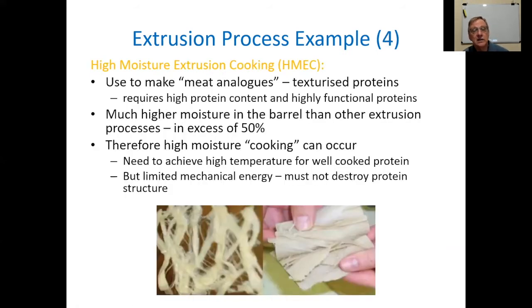And there's one other special, different process I want to mention. And this one is very topical at the moment because there's a lot of interest in alternatives to meat. This extrusion process is fundamentally different to most other extrusion processes in that it is operating at high moisture, generally well in excess of 50% moisture content in the barrel. We refer to it as high moisture extrusion cooking. We're also using very high protein content and highly functional proteins. And because we've got high moisture in the barrel, as we get the temperature up inside the extruder, we can get high moisture cooking reactions to occur.